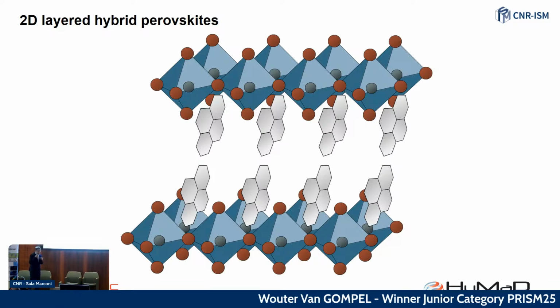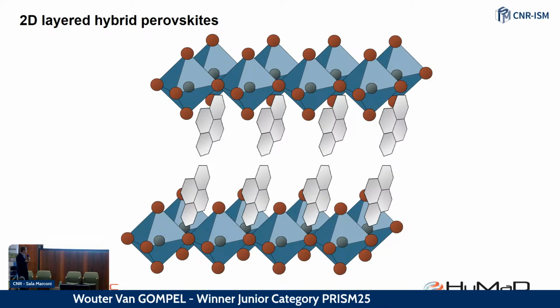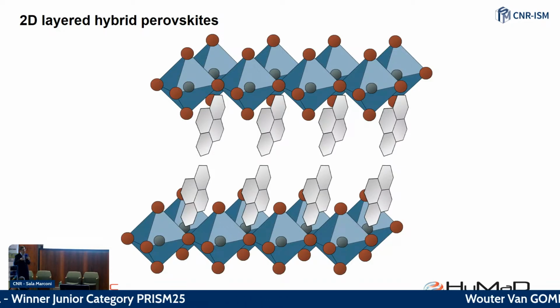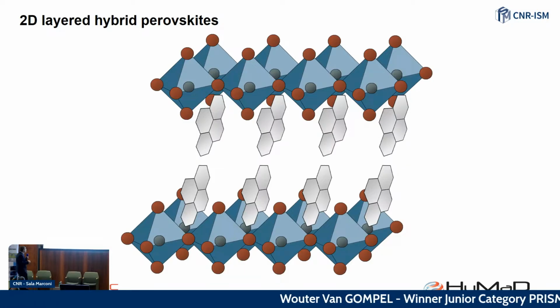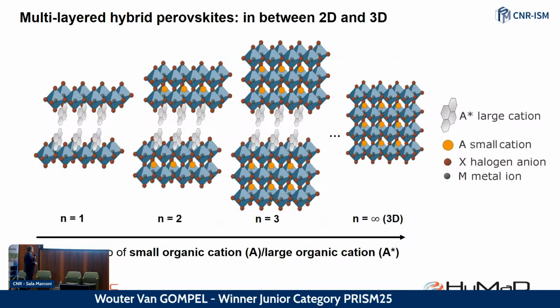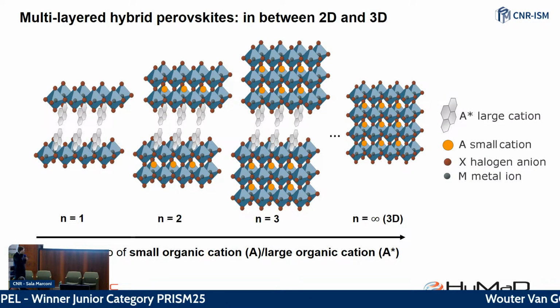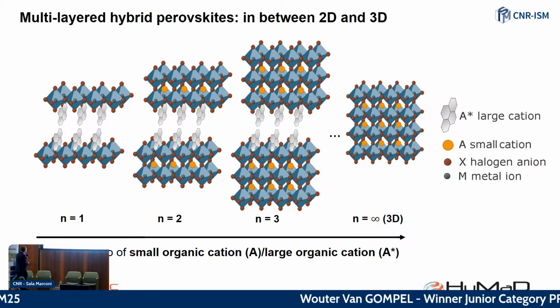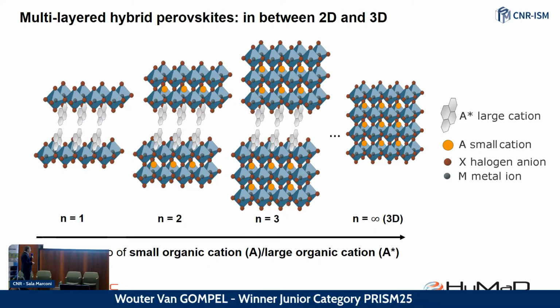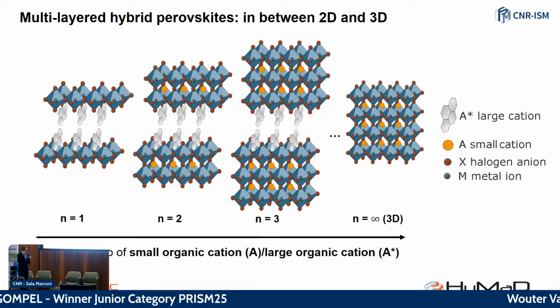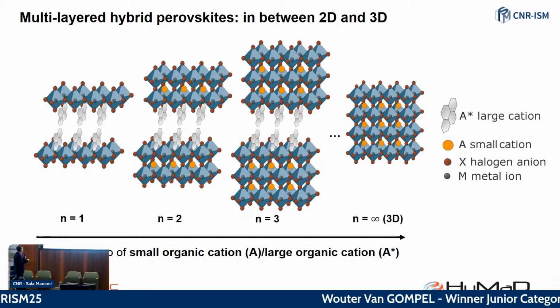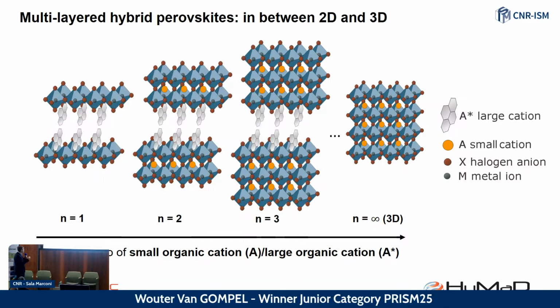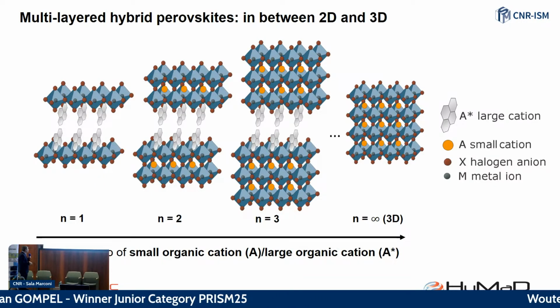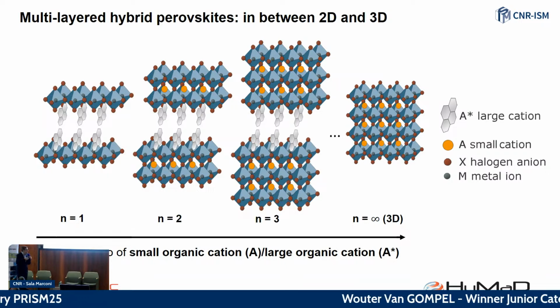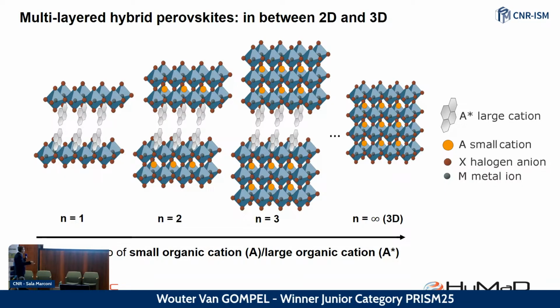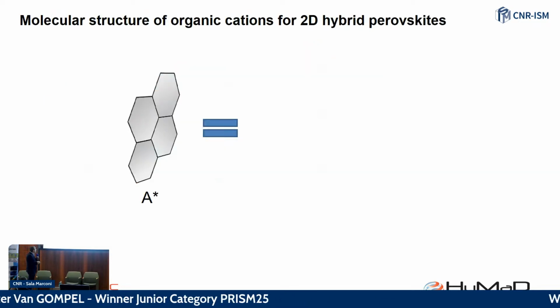And that's really the main focus of my research group, because it also involves a part of organic synthesis. So our group is a combined group of chemists, on the one hand inorganic chemistry and organic chemistry. And with these 2D perovskites, you can really insert more complex organic molecules. And then, there's also an interesting subclass of materials, which are called the multi-layered hybrid perovskites. So in between the 2D on the one end and the 3D on the other end, you can make variations, let's say. You can change the number of inorganic layers per organic layer from n=1 for the pure 2D to n=2, n=3, and so on, by playing with the ratio between these small organic cations, the typical A site, and then these bulkier organic cations. And they have then properties in between the pure 3D and the pure 2D in terms of band gap and electronic mobility and things like that. So there's quite a large playing field in that class of materials.